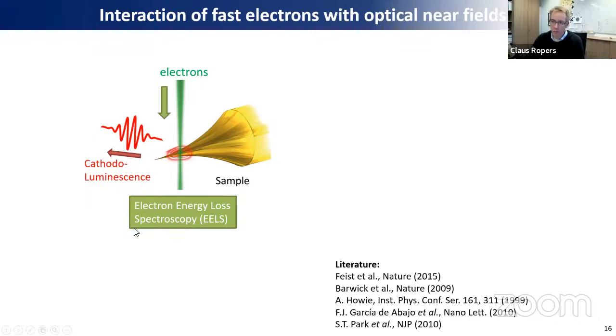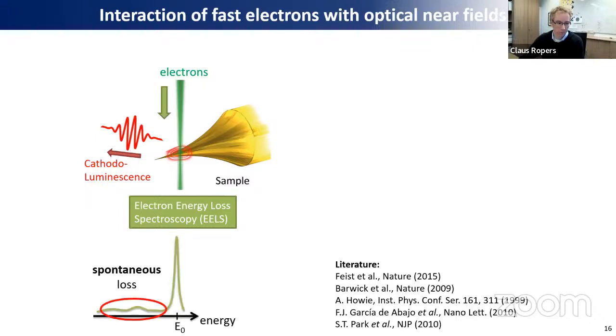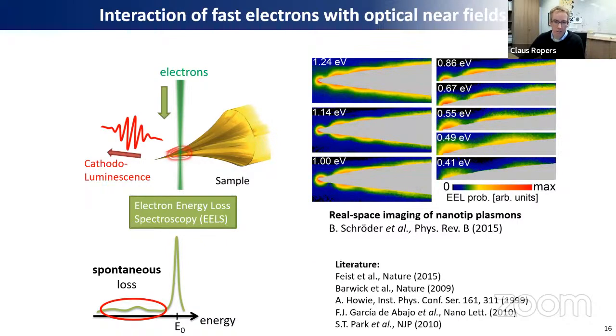Both processes, non-radiative and radiative decay of this polarization, will lead to electron energy loss, which can be spectroscopically probed, such that passing electrons near a structure or through a structure is going to produce a loss spectrum characteristic for a given material and nanostructure. So the distribution of electron energy loss events relative to the incident energy is going to give you a lot of information about the optical excitations, for example, in the material. You can use this by scanning the beam or having a parallel beam and then energy filtering. And if you look at different loss energies with respect to the incident energy, for example, here we characterized the plasmonic modes on one of these conical tips, producing standing wave patterns of plasmons propagating towards and away from the apex.